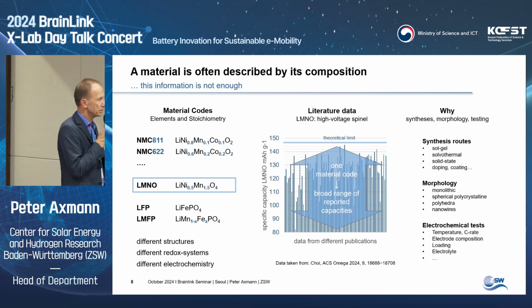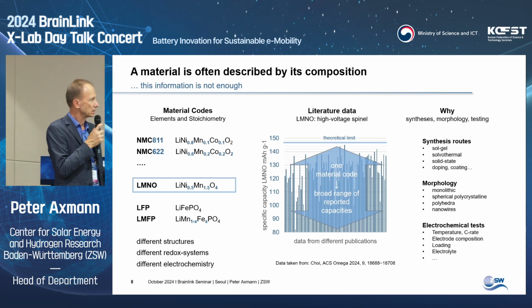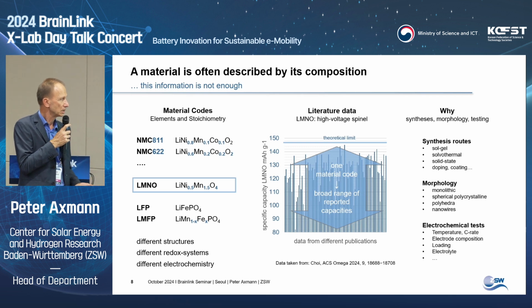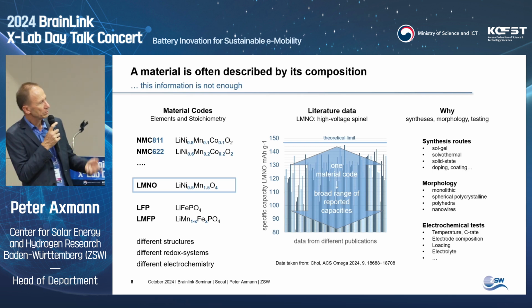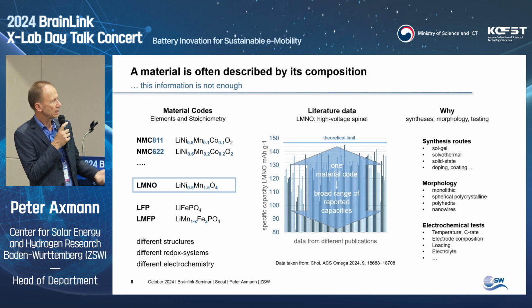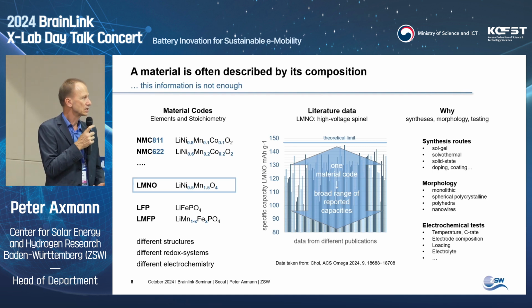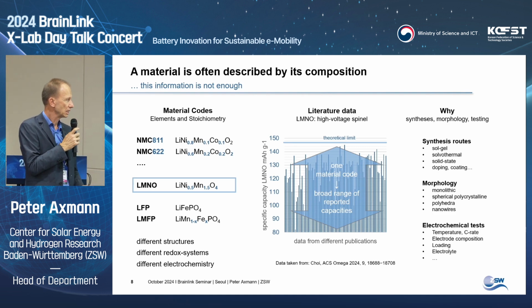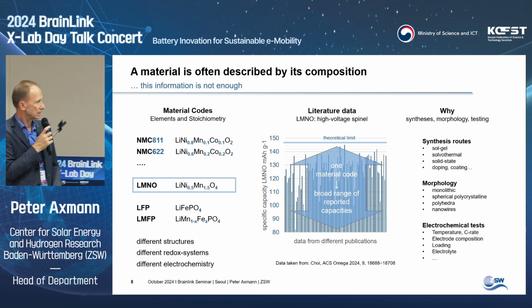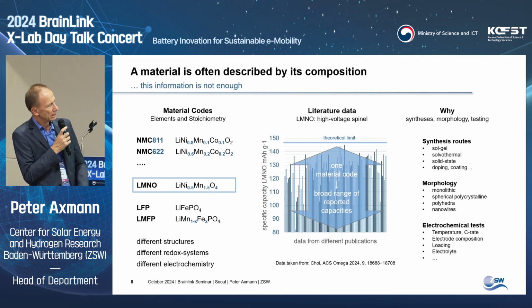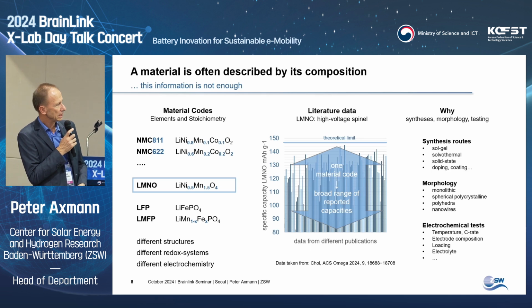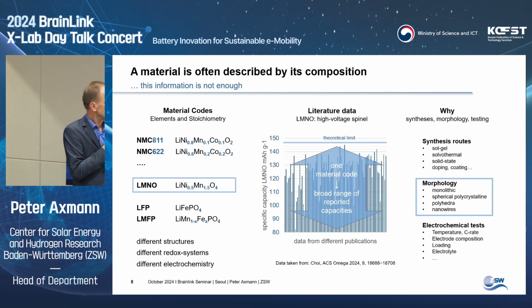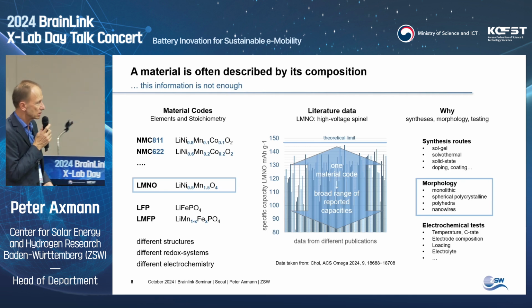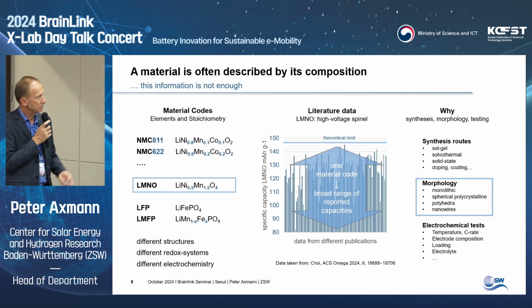Of course, you make the materials with different synthesis routes: sol gel, solvothermal, solid state routes. You have a different morphology. Monolithic materials are described, spherical polycrystalline materials, you have polyhedra, you have nanowires. And the electrochemical tests as well are different. They are cycled at different temperatures, C rate, electrode composition, loading. And what I would focus on is the morphology, because this is really important for this difference in behavior.